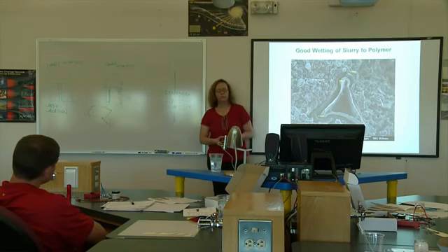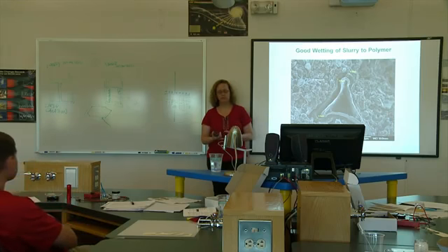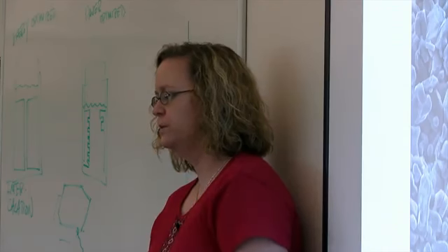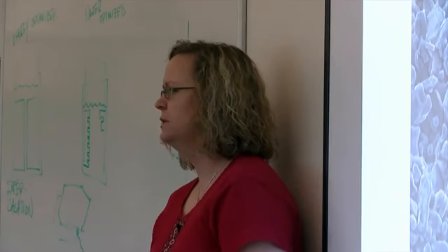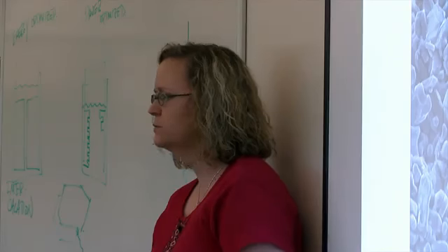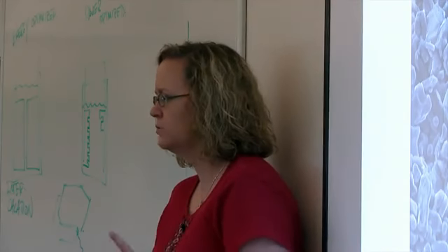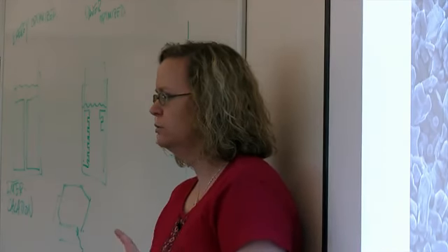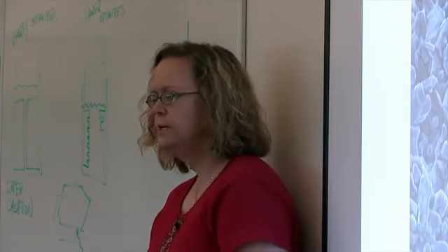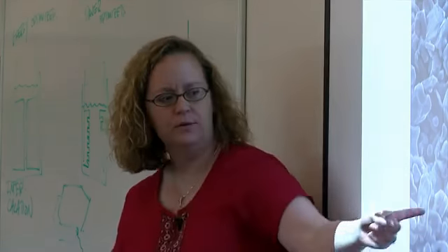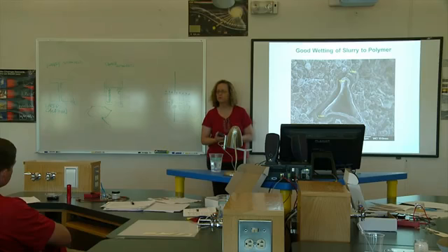So again, where we are today is the copper antimonide we know is really fast. It works, that part works really well. The slurry chemistry we've developed is also all water-based, and that's something that a lot of battery industry experts would tell you will never work, but it actually does work if you use new conductive additives. We can't use what they typically use, but we've designed some new ones that are safer and they're stable in water. But this polymer, the ionic conductivity is still too low. And by too low, I mean it's like 100 times too low. So if we cycle it in a hot oven, it works better.